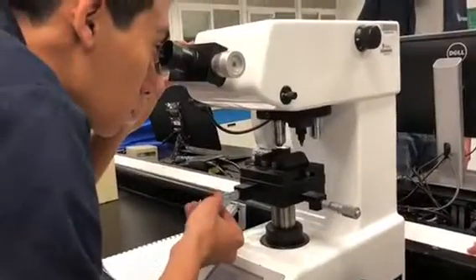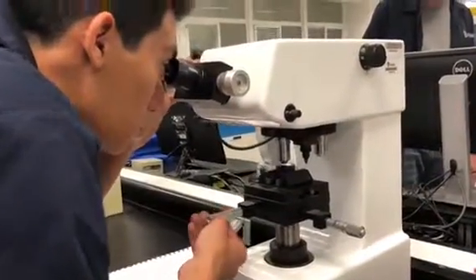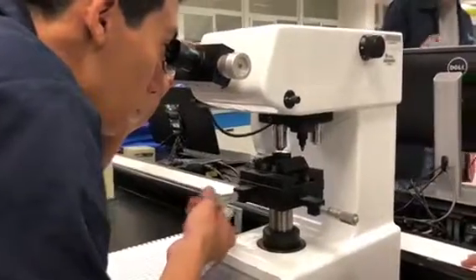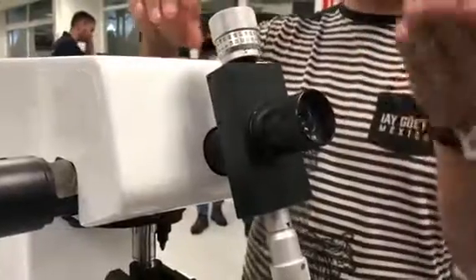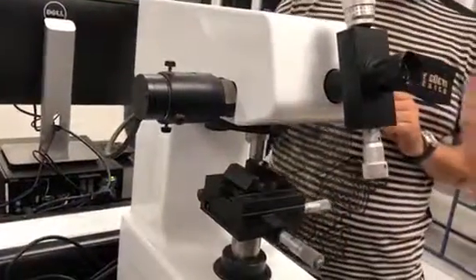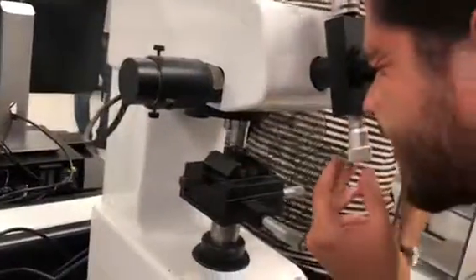For the practice, it was expected for the samples that were heat-treated through tempering to have a higher value of hardness over the samples that were not heat-treated. This was true for the 1045 steel, given that its hardness increased 11.5 points of hardness on the HV scale. For the 1018 steel, the hardness decreased in the heat-treated sample by 121 points of hardness on the HV scale.